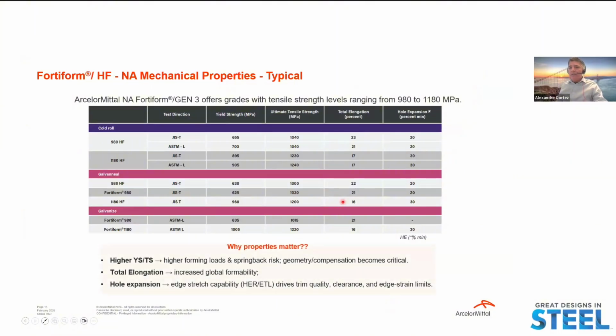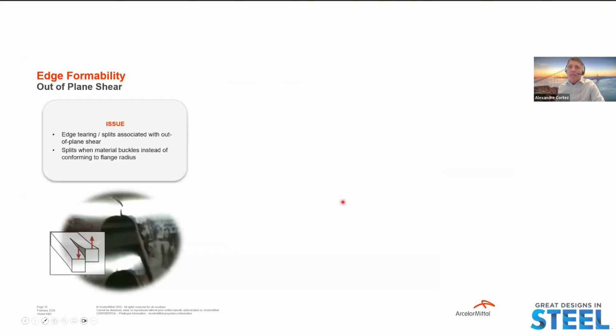Why do properties matter? Higher yield strength and tensile strength mean higher forming loads and spring back risk. Geometry compensation becomes critical. Total elongation increases global formability as well. Hole expansion, edge stretch capability, drives trim quality, clearance, and edge strain limits. And with that, let's talk about edge formability. Out of plane shear: the issue that we can find is edge tearing splits associated with out of plane shear, especially when the material buckles instead of conforming to the flange radius.